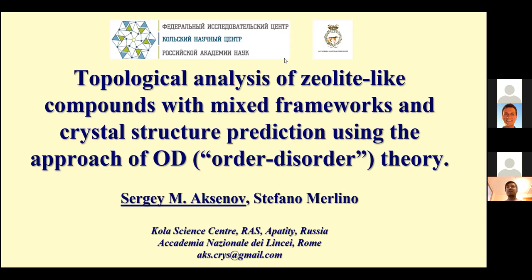What do I mean when I say zeolite-like compounds? Classical zeolites represent tetrahedral frameworks, where one oxygen is shared between two tetrahedral cations. In our case, we consider frameworks formed by two types of cations — tetrahedral and octahedral — keeping the requirement that one ligand oxygen is shared between two types of cations. We consider these as heteropolyhedral frameworks.